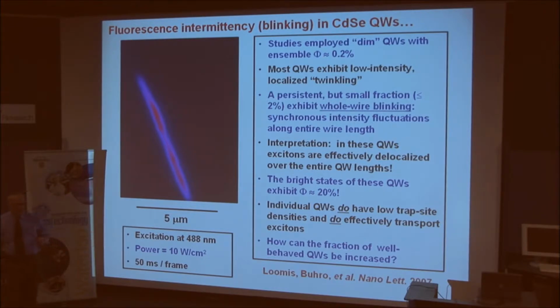And in fact, 98% of the wires in our specimens give exactly that kind of twinkling behavior. It's only 1 to 2% of our specimens that show this kind of synchronized, whole wire blinking. And moreover, when these rare wires are in their bright state, their individual photoluminescence efficiencies are 20%. That's competitive with rods. So the way we interpret this is that the whole wire blinking phenomenon reveals that excitons are able to be transported or delocalized along the entire length of the wire. Otherwise, we could not have this kind of synchronized blinking behavior.